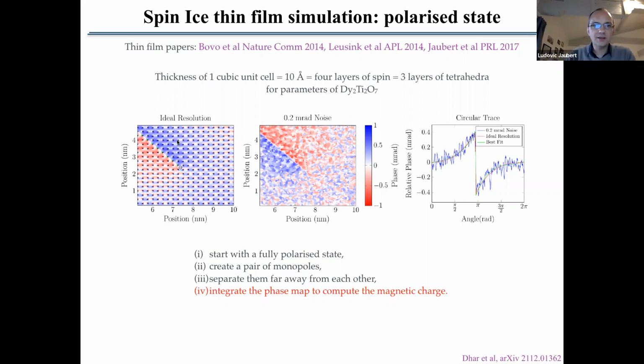And what we do here is that we put a strong magnetic field in the plane of the thin film. So we polarize all of the magnetic moments along the magnetic field, so that all of the spins are pointing this way. And then we flip 1 spin here, and we continue to flip a chain of spins there, which corresponds to this Dirac string between magnetic charges. So the point here is just, we start from a state where you have saturation, where you have 2 spins pointing in and 2 spins pointing out in all tetrahedra. So that's the ground state. And we artificially create an excitation, a magnetic charge there, a negative one. And the positive one, we move it step by step outside of the window of measurement. Okay. So here in this window, we only have 1 negative charge with 1 clear Dirac string.